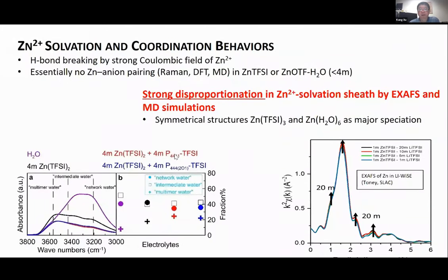So we did an extensive spectra study. We found that in the aqueous solution, even at the very high concentration of 4 molal, which is close to the saturation limit of the zinc salt, the zinc and the TFSI do not form very close ion pairs, which is very different from the case of lithium. And that's kind of surprising to us.